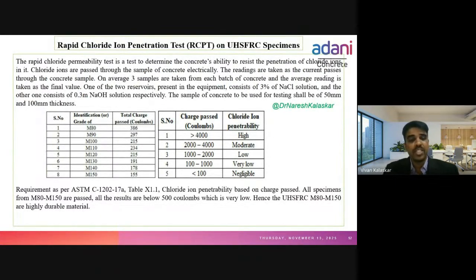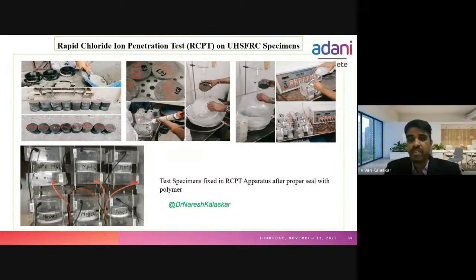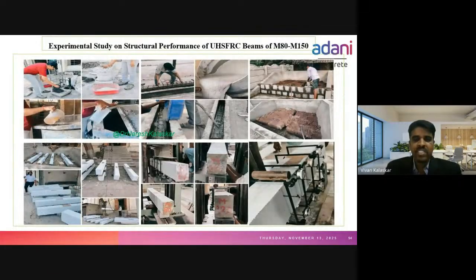Rapid chloride ion penetration test. For M150, we got 155 coulombs, which is a very low penetration when comparing with the table given in the code. So with these two parameters, water penetration and chloride ion penetration, we can say this ultra high performance concrete is an ultra durable concrete. These are some photographs of RCPT testing. In the coming days, we will also present the flexural behavior of ultra high performance concrete beams.